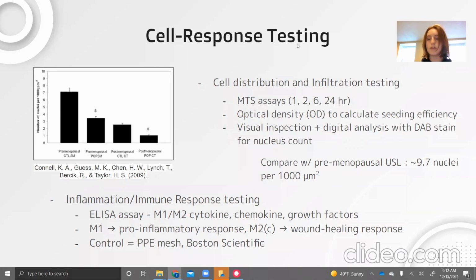We would compare the nucleus count to literature for premenopausal ligaments, and an ideal value would be roughly 9.7 nuclei per 1,000 micrometers squared. We would also test the inflammation or immune response using an ELISA assay. We'd be looking for M1 or M2 cytokines, chemokines, and growth factors. The presence of M1 cytokines would indicate a pro-inflammatory response, while the M2 cytokines, specifically the M2C type, would indicate a more positive wound healing response. These results would be controlled against the immune response for polypropylene mesh by Boston Scientific.